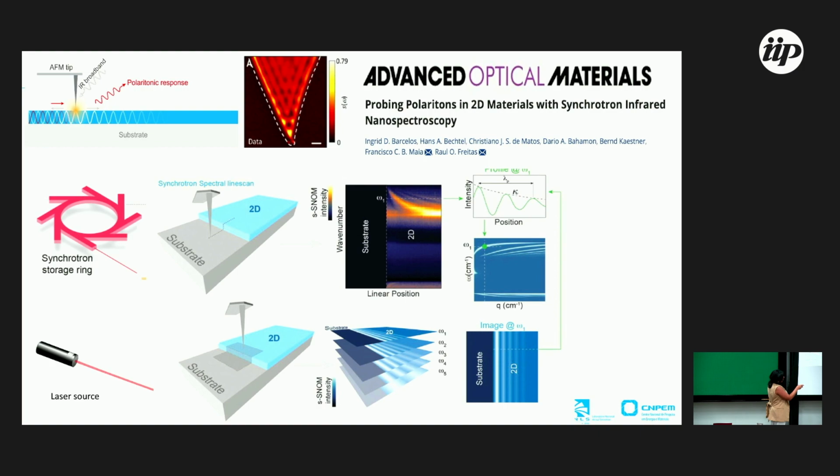This is, let's say, a damped wave, because there is loss in the real material, but we can extract the wavelength, the damping, the lifetime, and all those physical properties of this material, and we can compare directly with the theory without data treatment. So it's the most beautiful experiment where we can correlate theory and experiment, and we just don't need a sophisticated model for that.